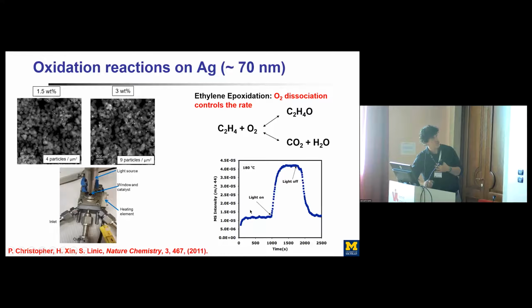So what you can see here is you start ethylene and oxygen, you have a certain thermal process going on, you shine solar intensity light on this system, and the reaction rate spikes quite dramatically. You turn the light off, the reaction rate goes down. And again, this is an oxidation reaction, so you can think of this as a steady state process that's monitoring the rate of oxygen dissociation. And you can think of ethylene as just a molecule that's coming in and picking that oxygen off the surface, allowing you to do steady state chemistry.